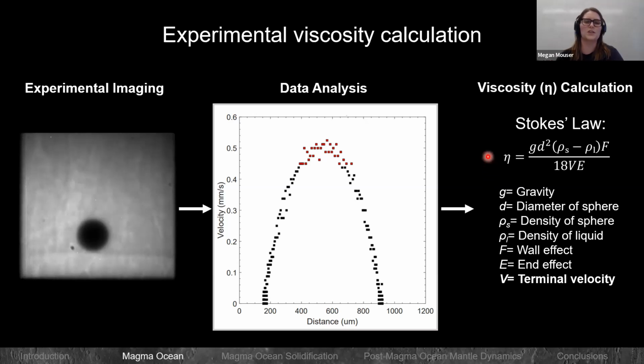Stokes' law takes into consideration a lot of different parameters, such as gravity, diameter and density of the sphere, and density of the liquid. There's also these two parameters, the wall and end effect. These parameters are important for working in these finite systems, and this capsule is a finite system, because you might notice that as the sphere gets very close to the bottom, it starts to slow a little bit. That has to do with how the liquid moves within this finite capsule, and so the wall and end effect can help correct for that.